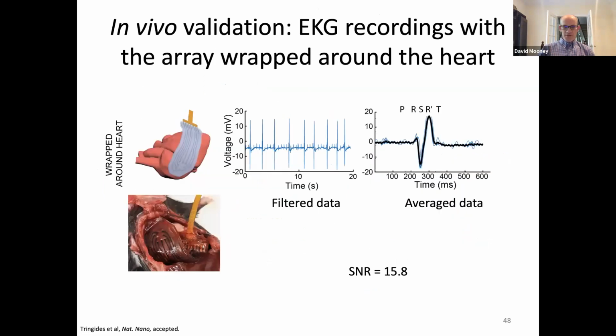Now, in terms of the ability to use these, a really nice feature is that because they're so soft and so conformable, we can use these in a variety of different anatomies. Here, for example, you're looking at EKG recordings where we've taken the array and wrapped it around a rodent heart. So it's bent almost 180 degrees. It maintains good contact and gives us excellent signals. In contrast, if we took a commercially available array and tried to do this kind of recording, we would have very poor ability to record because you'd have very minimal contact between the array and the underlying tissue.